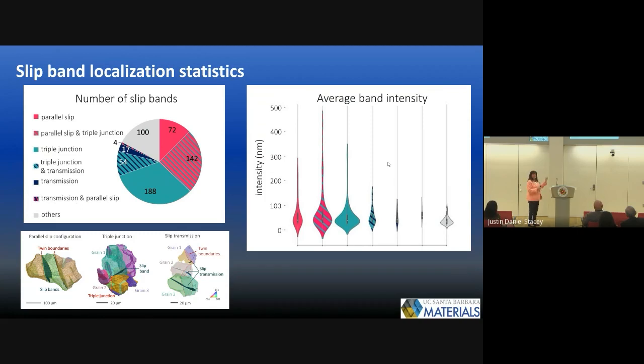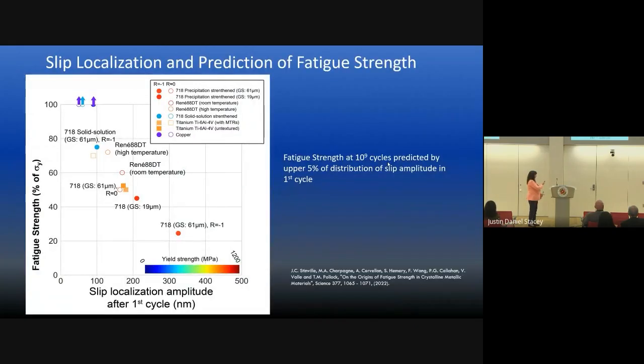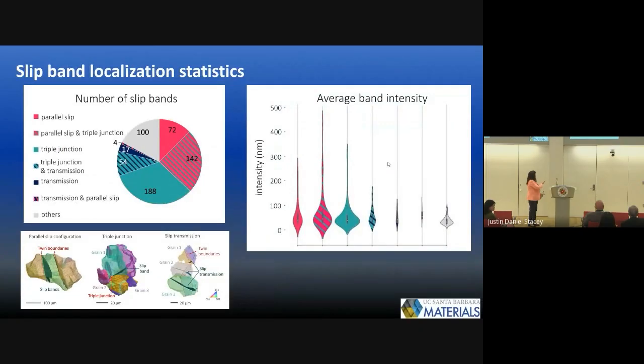We have those 3D data sets, so we can go and project where the high amplitude events on the surface were into the depth. And then by projecting them into the depth on the 3D data sets, that's how you find these kinds of events. So it's the combination that allowed us to find the more rare aspects of those irreversible slip events.